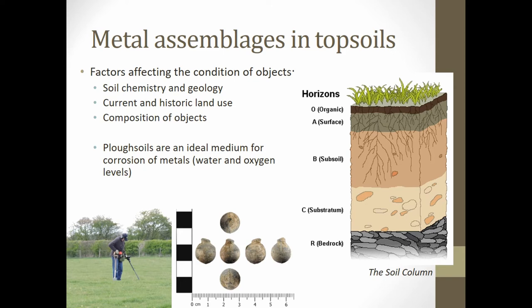Ploughing has been an issue for archaeological sites for decades, though less work focuses on the direct impact on assemblages and their condition. The act of ploughing churns and aerates the soil, altering its structure and chemical balance, making anything residing in that soil vulnerable to decay from mechanical and chemical damage. Ploughing can cause artefacts to break apart and encourage abrasion from soil particles, particularly in sandy soils. Corrosion also accelerates in this context, as it takes place more readily when there is a lot of water and oxygen available, making plough soils an ideal medium for this reaction.